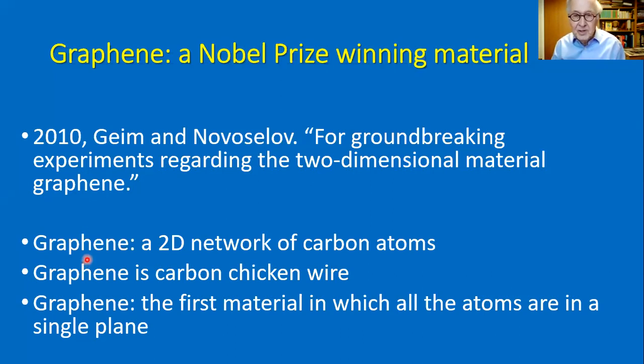But I'll just say in passing, it is, I believe, a mistake to think of graphene as a two-dimensional material. And I say that because you've got pi electrons above and below this two-dimensional plane. So when you're thinking of using graphene, it's rather important to remember you've got these pi electrons there, and it's actually a three-dimensional material. And you can define elastic tensors, 3D tensors, for example, for stresses and strains in monolayer graphene. So just think of monolayer graphene as a 3D material, although it's called a 2D material.